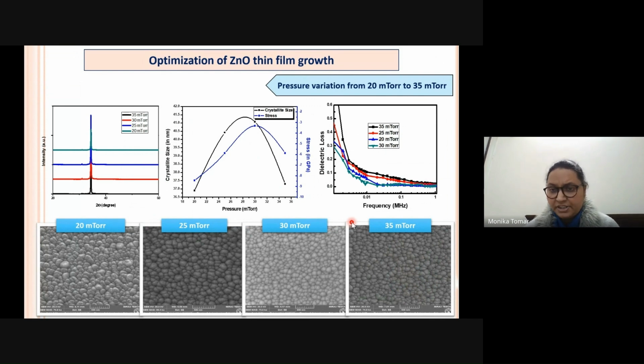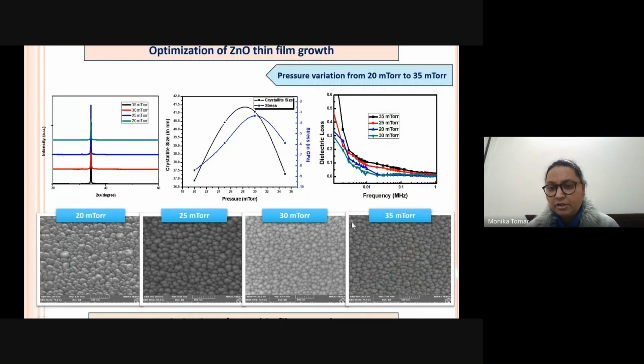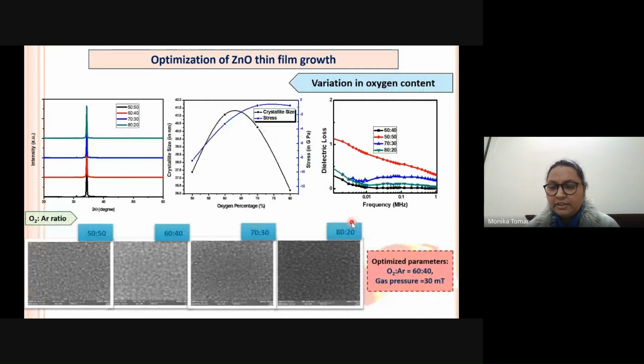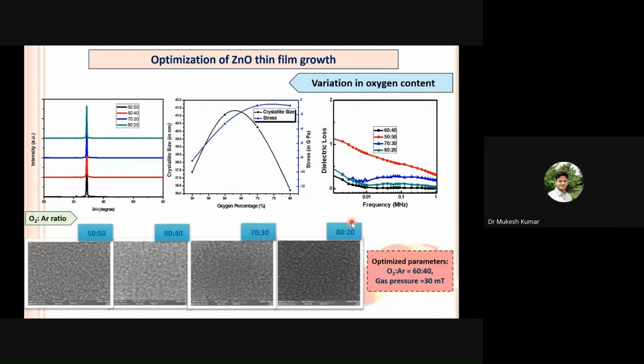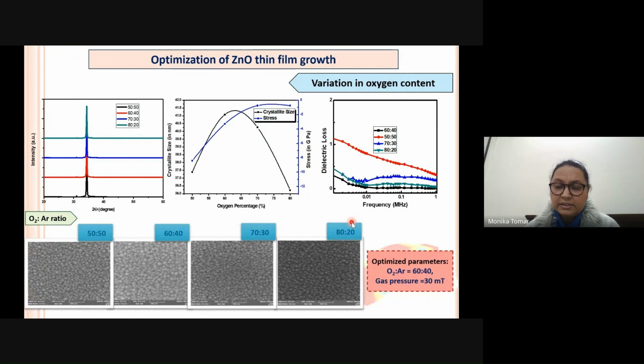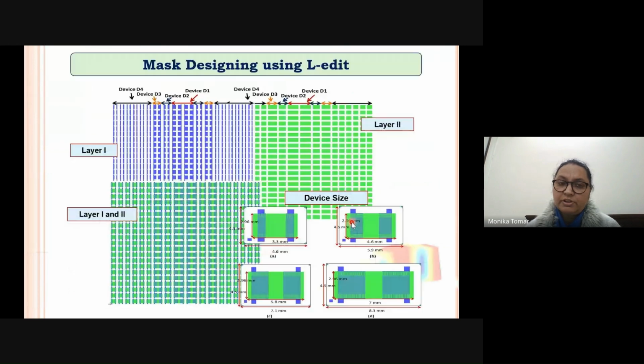So we have varied the pressure from 20 millitorr to 35 millitorr, and we have also varied the gas composition, the argon-oxygen ratio, with oxygen from 50% to 80%. We find that a particular composition of the oxygen-argon ratio of 60 to 40% and a gas pressure of 30 millitorr gives a zinc oxide thin film which has low losses, the surface is not very rough, and the film is good for the fabrication of the SAW devices.